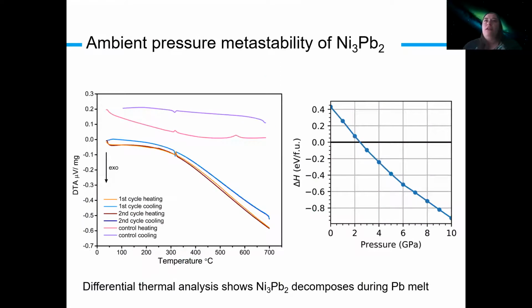syntheses. And one of the things that was particularly exciting to me was that this structure only decomposes once you heat it up to the lead melt. So we made this material at the lead melt at high pressure, and this material will stick around even upon heating and only decompose once you've reached the lead melt again. For completeness, I also included the formation enthalpies here, and at ambient pressure, this phase has a positive enthalpy of formation, indicating that it is in fact a metastable phase.